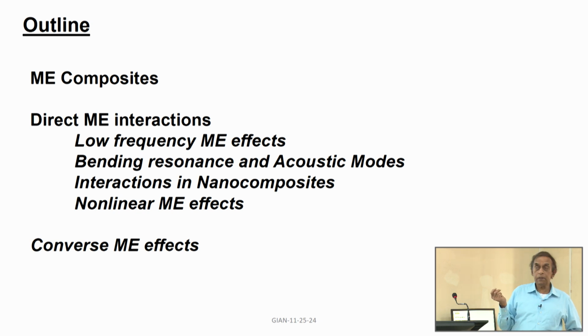So, the converse effect is the effect of the electric field on magnetic properties. It can be magnetization or magnetic anisotropy, or you look at the magnetic force microscopy and you look at the magnetic domains, then you apply a voltage or electric field, the domain will undergo a change. You can measure the MFM amplitude or phase based on what happens to the phase or the amplitude under electric field. You can put together an estimate of the converse magnetoelectric effect. Okay. So, these are different ways of measuring some of the interaction between the two phases.